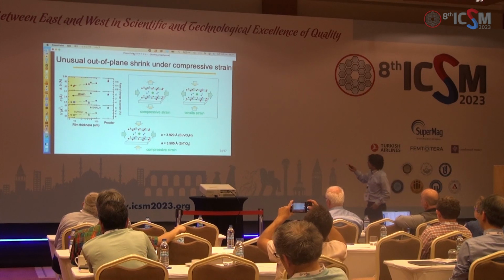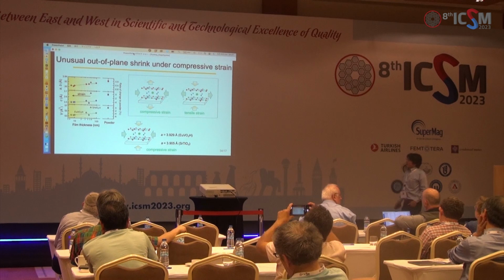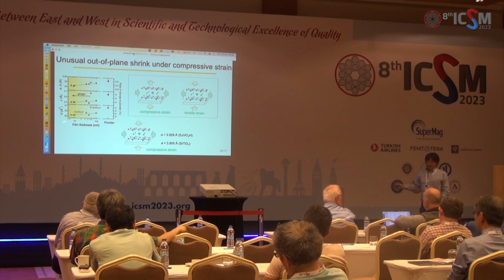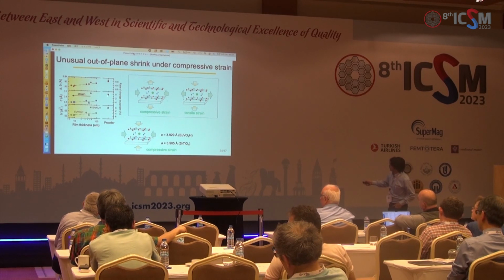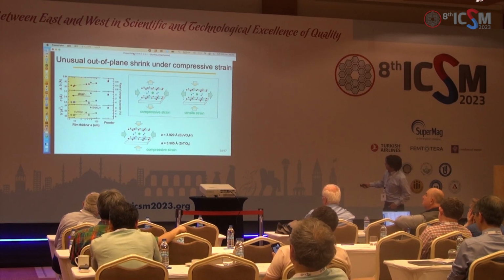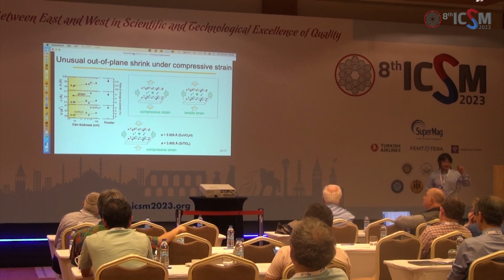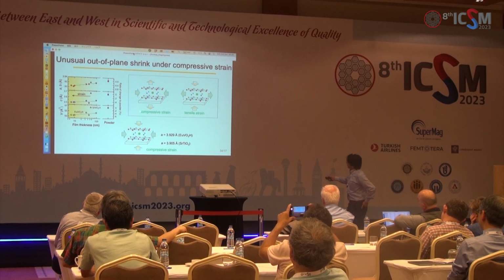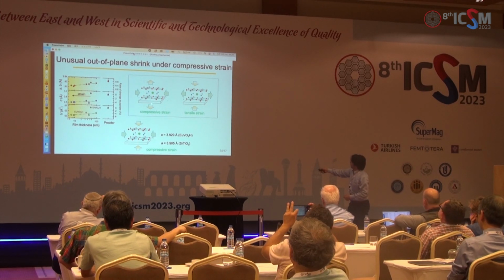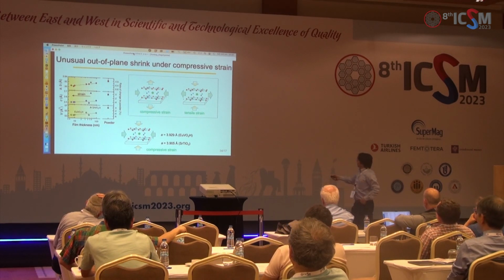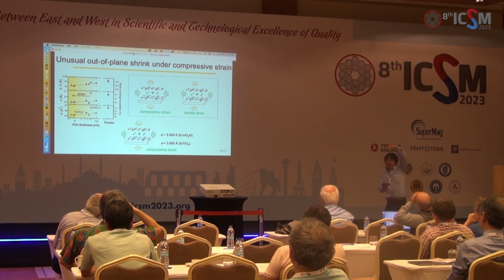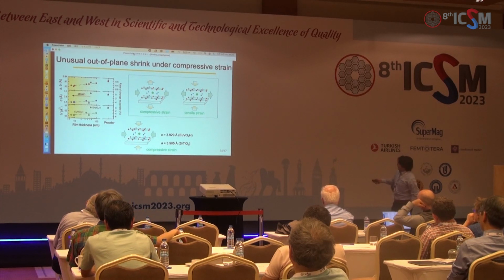Then the key for this unusual behavior is obtained by looking at the lattice parameter evolution. This is the lattice parameter, the a-axis, b, c-axis, and volume of the powder sample. But as you can see, when you decrease the thickness from here to here, the a-axis and the c-axis are both reduced. But this is unusual. Normally, when you apply biaxial compressive strain, the c-axis, the out-of-plane axis, should be elongated. However, in the case of tensile strain, the c-axis should be reduced. But what is happening is both axes are reduced. So the a-axis and c-axis are both reduced in these thin films.